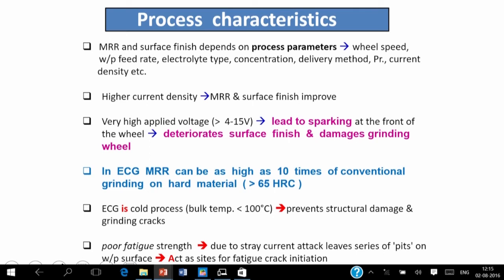But if we increase the voltage more than 4 to 15 volt, it leads to sparking at the front of the wheel, and it deteriorates the surface finish and damages the grinding wheel. In electrochemical grinding, the material removal rate is as high as 10 times higher than the material removal rate in conventional machining for a 65 HRC workpiece.